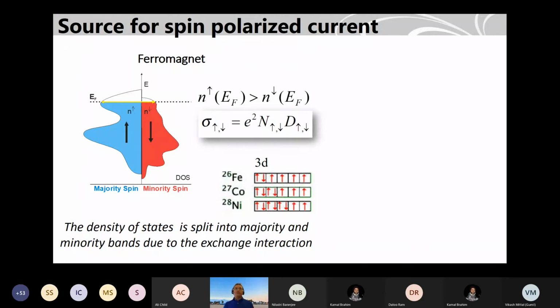So you have to look for spin polarized electrons. Do you know from where you can get spin polarized electrons? They are mostly ferromagnets, for example, iron, cobalt, nickel. They are magnets at room temperature. If you look at the density of states at the Fermi level, you have more upspin electrons than downspin. So the density of states is different. That means the conductivity for the up and down spin electrons will also be different, and that depends on the diffusion constant of electrons. So the up and down electrons will be different.